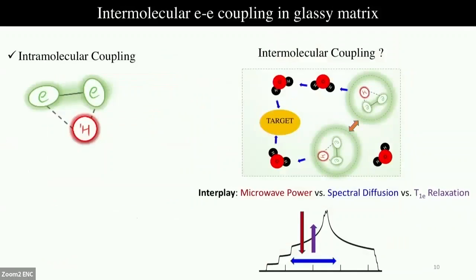So this was the first part of my talk, where I focused just on the intramolecular coupling in order to maximize the cross effect. Many times when we do DNP experiments, we run at a sample concentration where the intermolecular interaction cannot be avoided. And if we had to make a guess, we would say that if these interactions are there, then the relaxation of electrons would become very fast and we may end up having a lower DNP. But this in general is not true.